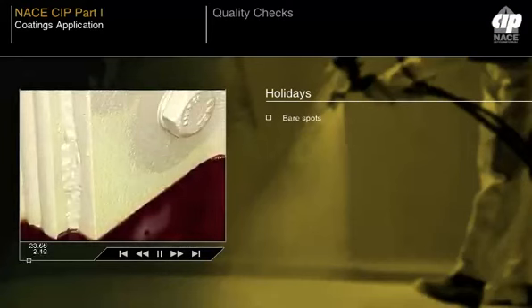Holidays are bare spots, misses, or even thin spots in a coating where the substrate is uncoated. They are generally more significant when the coatings are linings intended for immersion service. Pinpoint corrosion can occur, and premature coating failure is likely to be associated with any holiday.